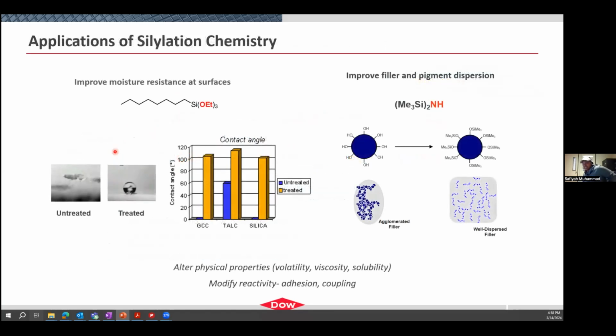Some of the areas of silylation chemistry is it's used to treat surfaces to improve moisture resistance. So if you think about putting Rain-X on your windshield to allow the water to bead off, that's silylation chemistry, right? If you take a silane with a hydrophobic tail on it, and you add it to a surface which can be silylated, then you can now have a hydrophobic surface so that water has a higher contact angle and beads off as opposed to spreading out on your surface.